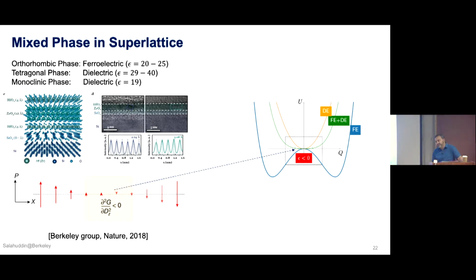You are absolutely correct. When we are looking from the entire system, it cannot be in negative capacitance region. It will be thermodynamically unstable. Therefore, it will give us what we call a hysteresis. It will switch between two states. However, what we can do, and this is what we have imaged, is that we can locally stabilize this negative capacitance region, which is surrounded by positive capacitance regions. So when you measure from outside, you still see a positive capacitance, but it is highly enhanced compared to what would otherwise be. Yeah. All right.